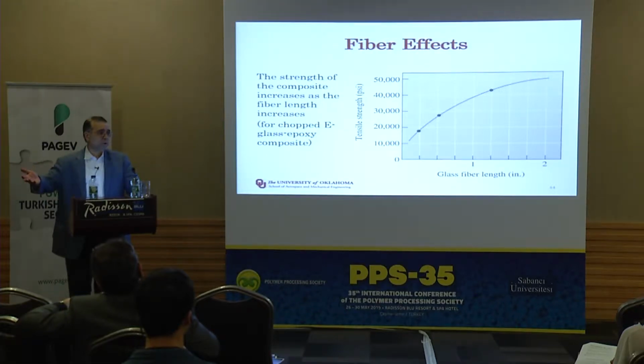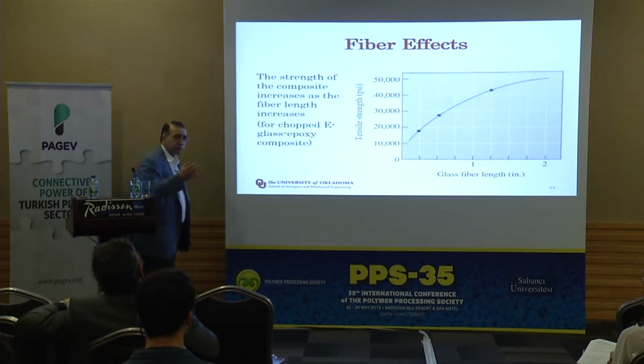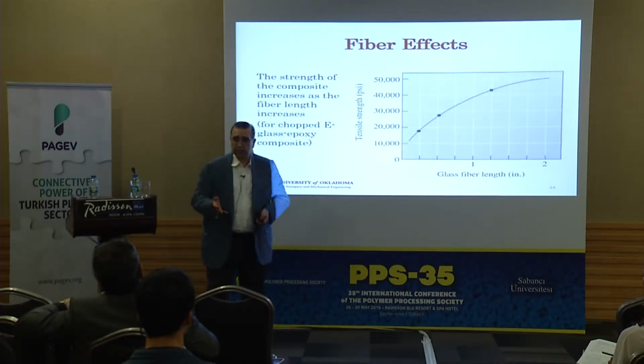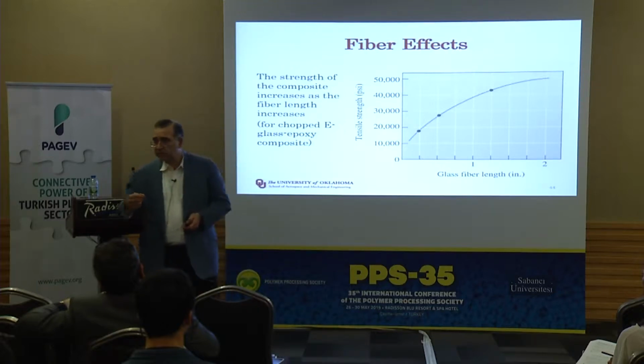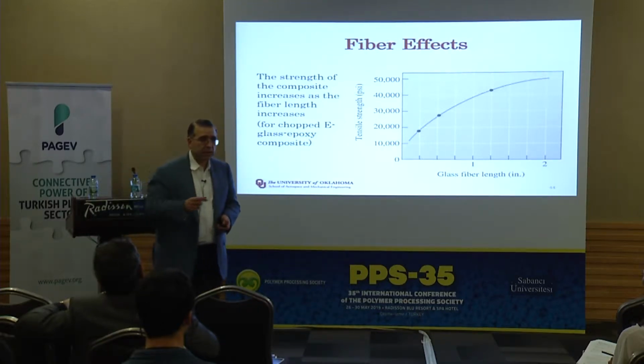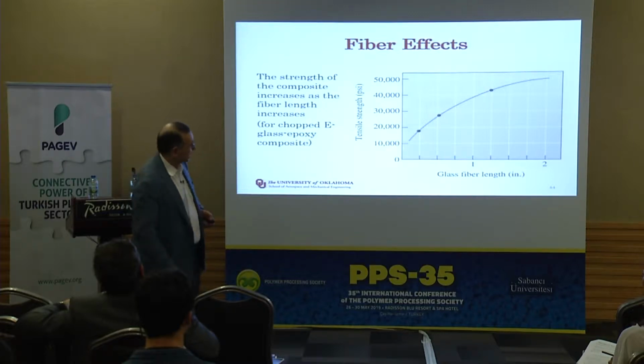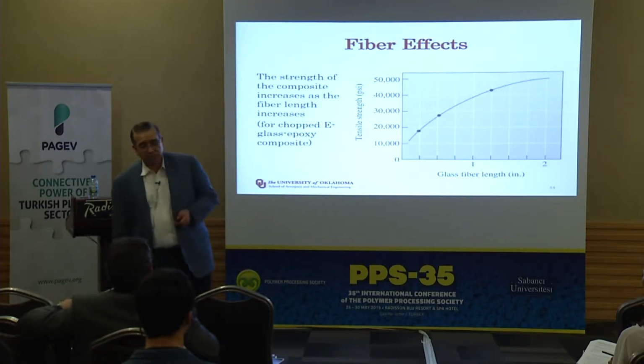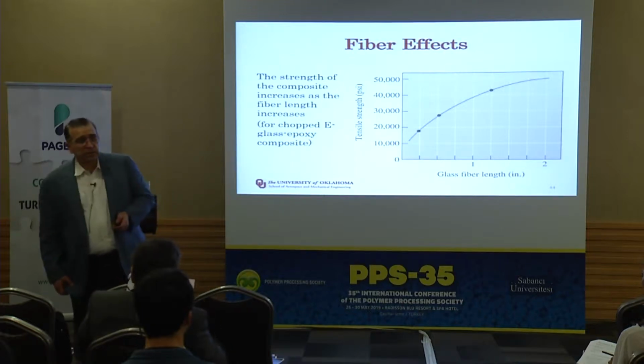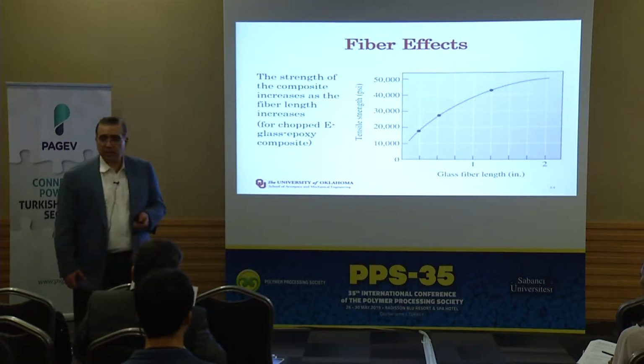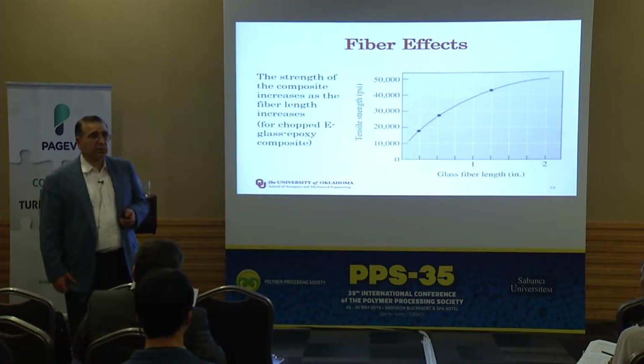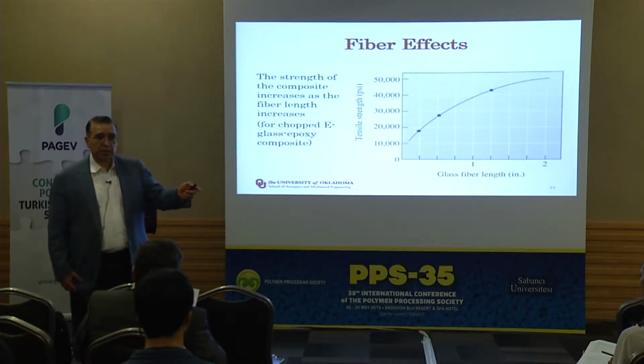If you are doing injection molding, you have the extruder and you have the mold. So as you go through the process, your fiber length will become smaller and smaller. Even if you try to use a longer fiber to start with, you put it in your pellet and the hopper, but the extruder will essentially degrade and reduce the length of the fiber. So 20, 30 years ago, people looked at a lot of extruder design to minimize the degradation of the fiber length. Okay, so that's another thing that you need to know if you are doing injection molding.